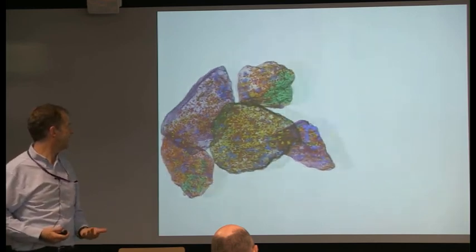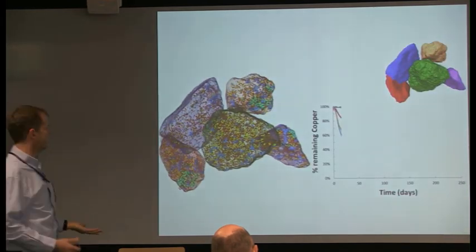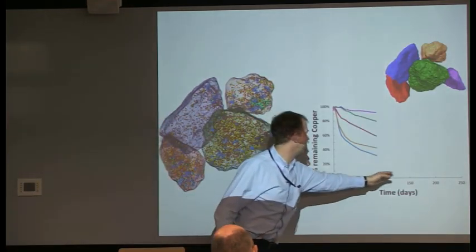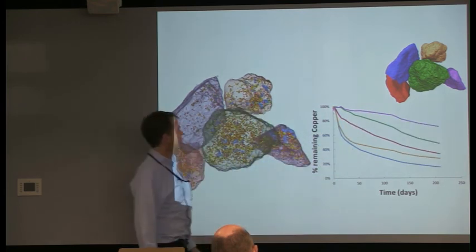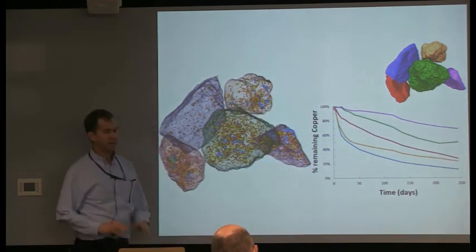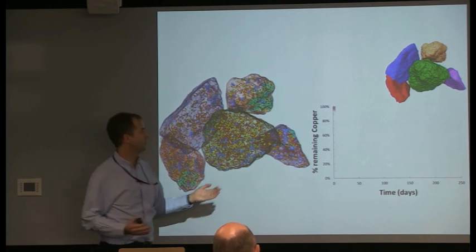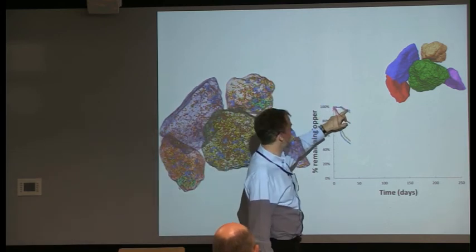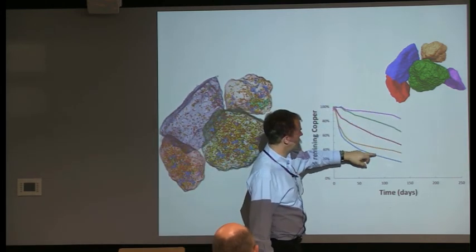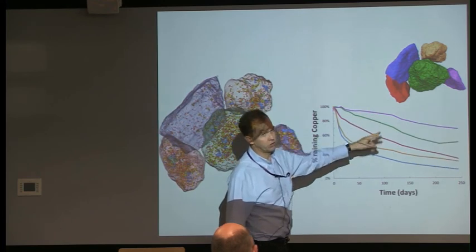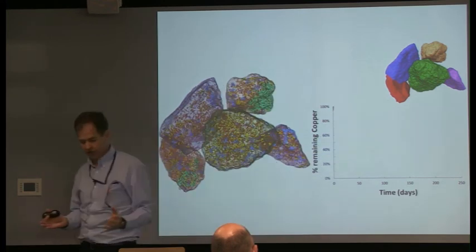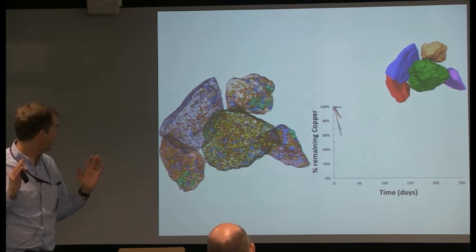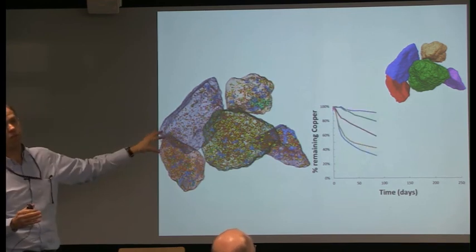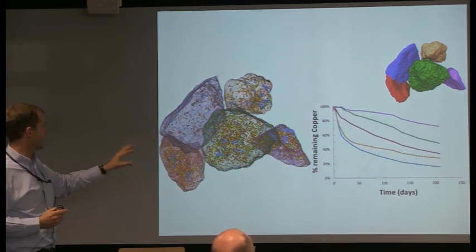And what you'd expect is that all of those, as we're leaching over a period of almost a year, would dissolve at about the same rate. These are completely picked at random, and what you see is a range in rates of leaching that spans a huge variation. Any of the processes you're looking at in terms of environmental radiation waste is going to have the same range of statistics, and it's huge.